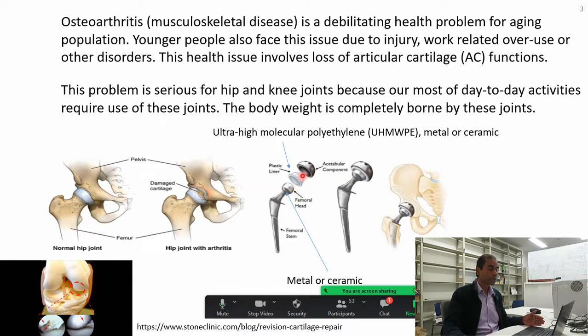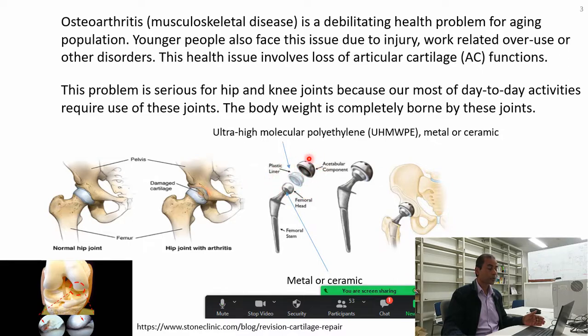Most implants have either a metal or ceramic femoral head and a polymeric acetabular cup. Although UHMWPE gives very low coefficient of friction and wear in general, the coefficient of friction needed is in the range of 0.001 or even less. Under this situation, UHMWPE actually wears, and even though it is the best current solution, it still has a wear problem.